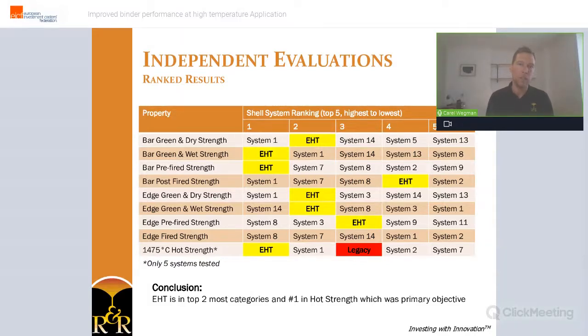but that's actually good for shell removal, so seen as a benefit. So even though we were officially really focused on the hot property improvements, we were very pleased that the green performance was doing very good versus the other 15 candidates.